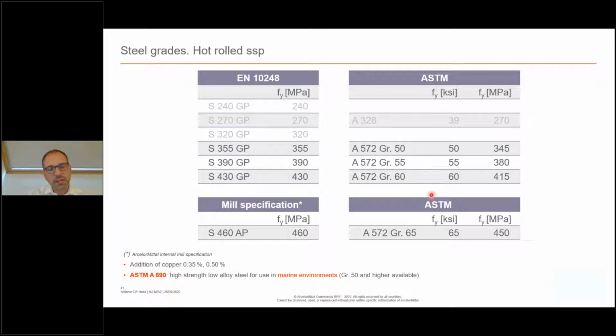You've also seen this slide in the first webinar. However, I grayed out all those low yield strengths because, as I said, if you use steel that's produced in an electric arc furnace, nowadays S355 GP is the minimum that you can achieve. So there is no difference in pricing normally if you use a 240 or 355. This is different for sections. We are talking about sheet pile. We're not talking about other products.